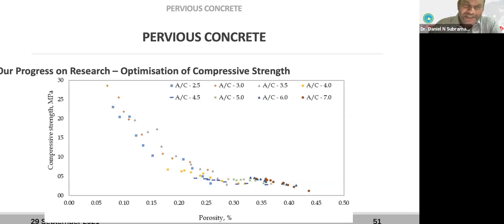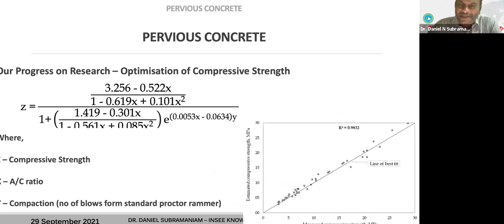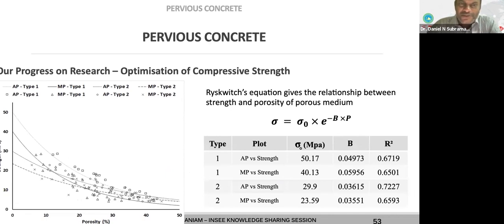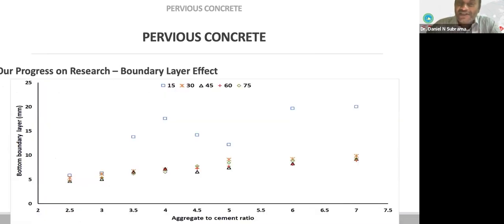So this is another model that can predict the pervious concrete porosity and compressive strength. This can be depicted by a mathematical equation this way, right? But you can see the very good fit as well, and you should be able to predict the outcome as well before any mixing. So this is another model that is also available to predict the compressive strength based on the porosity, which is a widely used model for porous material. Now, for example, powder technology. So Ryshkewitch equation is actually applied for powder, and also it is applied for porous concrete in some studies. So that's why we went for this, and we found out that they also satisfactorily predict.